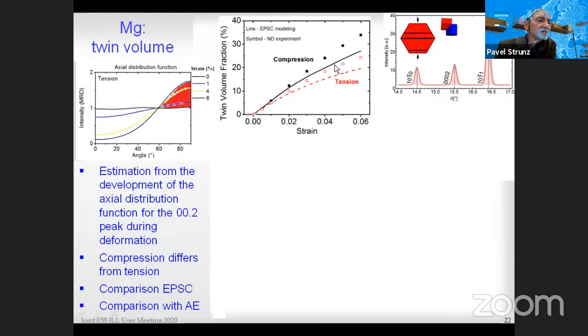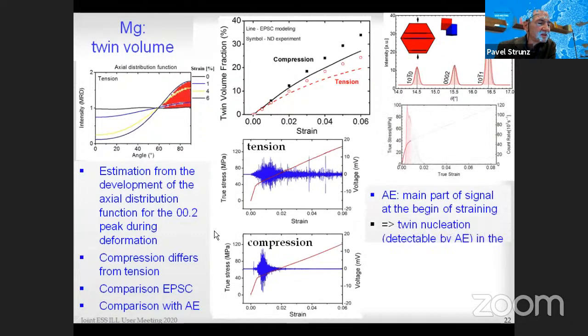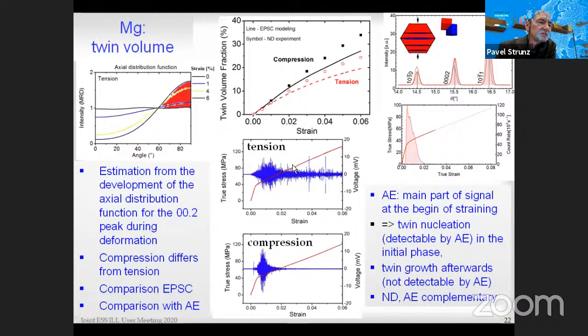Those are these straight lines. The trend is the same. You can see that the model also predicts the difference between compression and tension. It can be also said that the model could be still a little bit improved to fit better with the measured data. When we compare with acoustic emission signal, we can see that at the beginning of